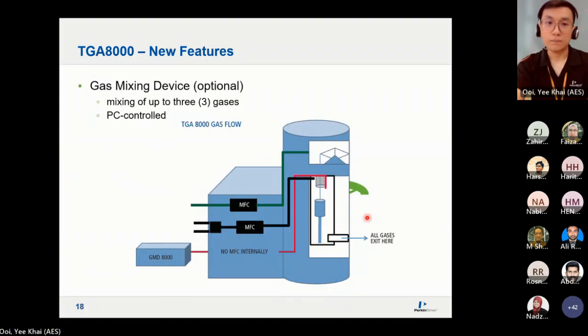Okay, so we have another accessory called the GMD. All our TGAs have a built-in MFC, which we call a mass flow controller. Beside the heating rate and the temperature range that we can heat up to, another thing that we can control is what we call the gas flow rate, or the purge gas. In TGA, most commonly we use nitrogen, but some people use oxygen as well. But nitrogen is a must because your balance requires purging as well.